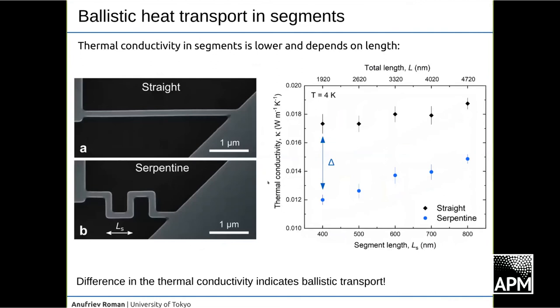Basically, here we can calculate the thermal conductivity of one and the other as a function of segment length. We can see that, of course, the thermal conductivity of the serpentine will be lower than the straight one. But as we increase the segment length, the difference tends to become smaller and smaller, because if the segment is too long, then it doesn't matter if some phonons can scatter backward, because most phonons can still go through the whole segment ballistically. And this is a way we can probe the length scale of ballistic conduction, actually.